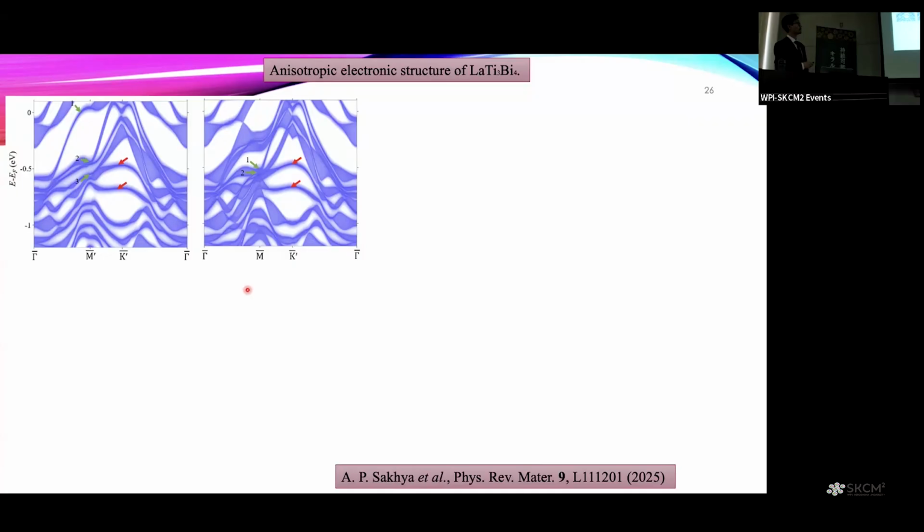In gamma m prime, you have a band of singularity near the Fermi level, whereas along gamma m, you do not have a band of singularity. You also have a slight change in the dispersion of the flat bands. Though it's slightly more difficult to track this in experiments because the flat band intensity is not very great, at least we could see these changes very easily.